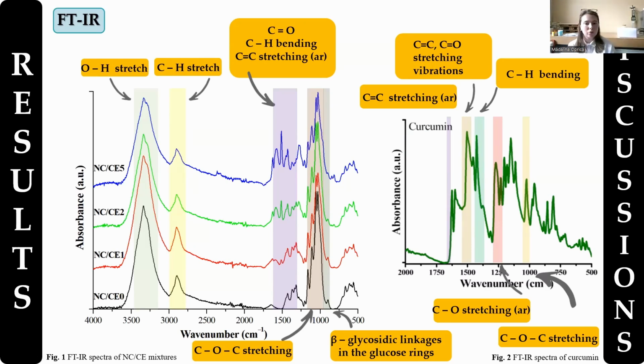The presence of curcumin is attested from the band with a peak at 1626 centimeters at -1, attributed to the double carbon bonds of the aromatic ring, while another band with a peak at 1501 centimeters at -1 corresponds to the carbon-oxygen double bond as well as to the carbon double bonds vibrations. The stretching vibrations of the carbon-oxygen group with aromatic character are also present in the spectra, as well as the etheric stretching at 1028 centimeters at -1.